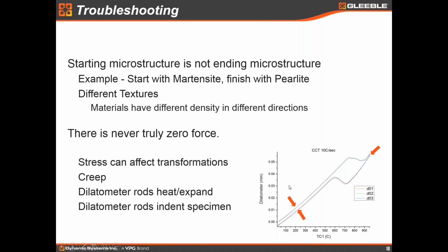Another thing that could be happening is that these are rolled samples. Whenever you do a rolling deformation, you get a texture in the material. So the material will not be truly isotropic, but will have a rolled texture with preferential crystallographic orientation through the product. Once I heat that product up and cool it back down, I've randomized that texture, and I've probably changed the dimensions a little bit, simply because different crystallographic planes have different densities. If I change those crystallographic planes, I will change those densities. That's a very small effect, and I doubt that's what we're seeing here in this graph, but it is something else to keep in mind.